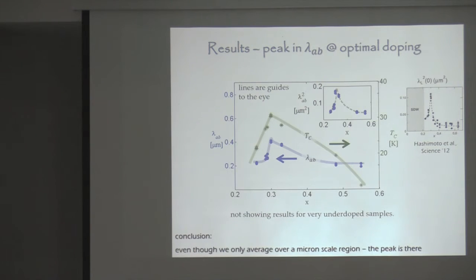So we did this for this whole sequence of samples. And you can see in this plot, this axis shows you the penetration depth itself, and you see that it has a bump near optimal doping. And we know that this is optimal doping because we also measured TC at exactly the same point where we measure lambda. The way we do this is we find a clean spot, we do a touchdown at low temperature, get lambda, and then increase the temperature until we lose the signal, and then we know TC there.